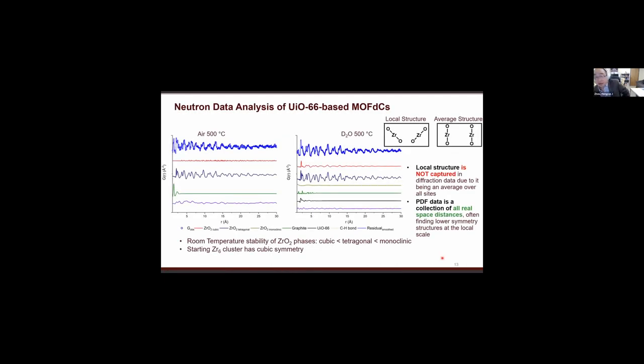Okay, so the local structure is not captured in diffraction data due to it being an average over all sites. For example, this represents the local structure, but it's an average structure. When you have this PDF analysis, the PDF data is a collection of all real space distances, often finding lower symmetry structures at the local scale.